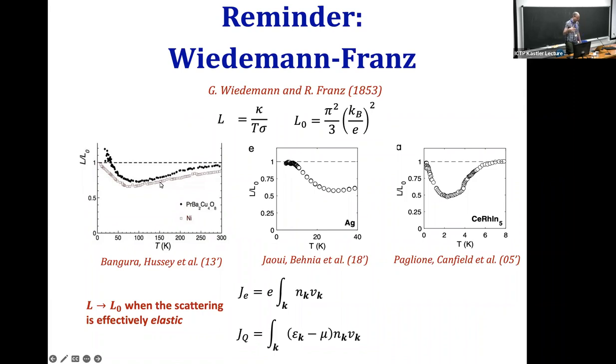But as you raise the temperature, as soon as the temperature exceeds some typical frequency of the phonons, the scattering from phonons becomes quasi-elastic again. The phonons can only absorb energy of order their frequency. And when the temperature is higher than that, then the scattering from phonons is essentially elastic. This is why the Wiedemann-Franz law actually recovers at high temperatures again. This is a very, very typical behavior in many metals.